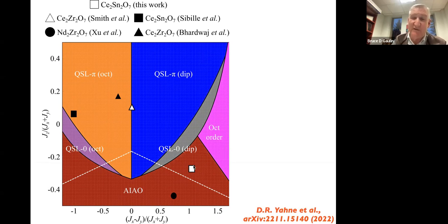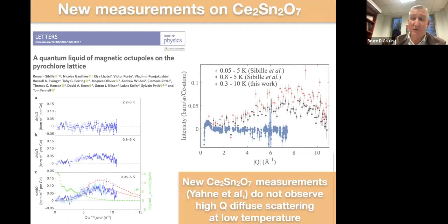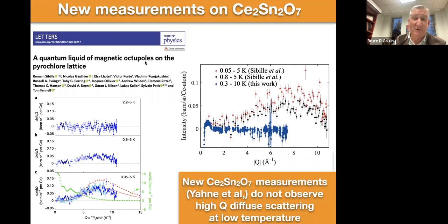At any rate, where we would place this on this phase diagram is far removed from the area where the Sibille et al. group would place cerium stannate, based on their earlier measurements. Among their earlier measurements were measurements of diffuse scattering at high Q, which were interpreted in terms of a quantum liquid of magnetic octupoles. It's a very nice, very interesting paper, and I can find no fault with the paper or its analysis. But they report this temperature dependent diffuse scattering at high Q that they attribute to a liquid of magnetic octupoles. At least in our new samples of cerium stannate, we do not reproduce that diffuse scattering at high Q. We do have diffuse scattering at low Q, but not at high Q.